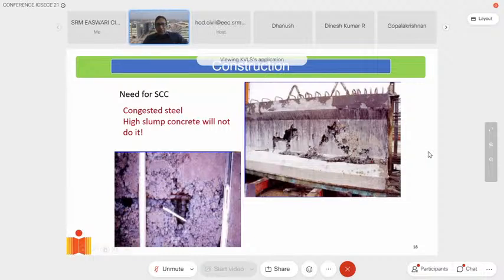And soon it became obvious, as I'm showing you this example, that when you have heavy steel congestion, just making concrete of a high slump won't do it. Concrete will not penetrate through all the small gaps that you have with very tight reinforcement. That's where people started realizing that now flow has to be looked at. We need to look at the flow behavior of concrete, and slump does not provide a solution, or it does not indicate anything about the flow of concrete.